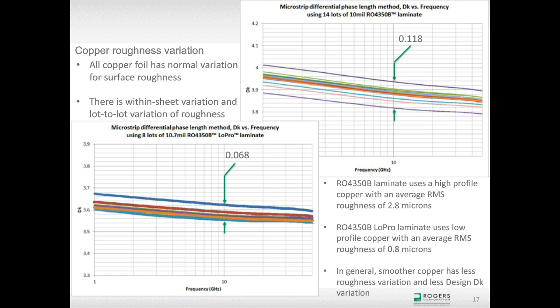So I did an experiment where we kept the same substrate, so we have minimal substrate dielectric constant variation, kept the same substrate, same lot of material, same everything. The only difference was we used 14 different lots of copper that had different roughness and in the range that we expect the roughness to vary. And made my circuits, did the microstrip differential phase length method, and the upper right chart is showing the range of design Dk that we see from just copper roughness variation only.